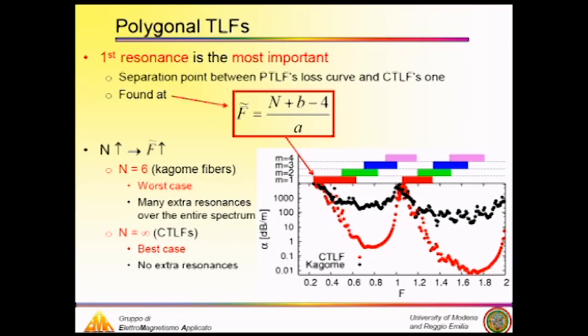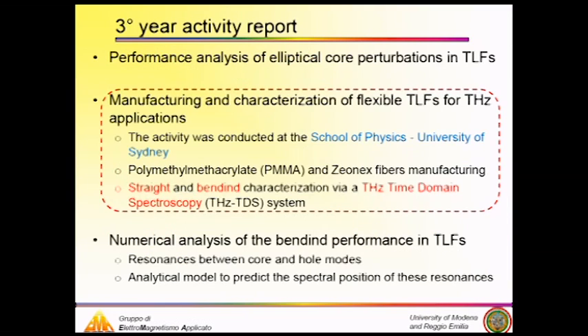Kagome fibers, having n equal to 6, a hexagon, represent the worst case since, as shown here by our model, it's full of extra resonance over the entire spectrum, whereas the circular case shifts this extra resonance to an infinite frequency, making it the best case that we can achieve. So, this is a short summary of the activity that I've done during this last year of PhD.